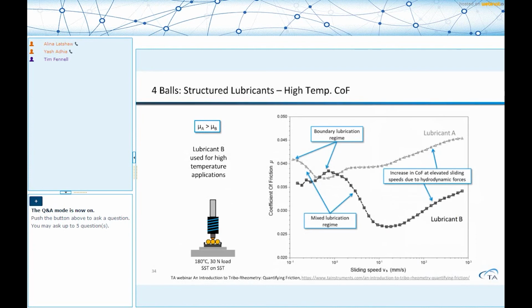Some examples I've taken from the previous webinar. They're explained in a lot more detail. But here we're just showing you how coefficient of friction changes as a function of sliding speed. Here we are making the measurement at 180 degrees Celsius, so very high temperature. And you can identify the different regimes, but at a very high level, you can at least appreciate that lubricant B is the material of choice over here.